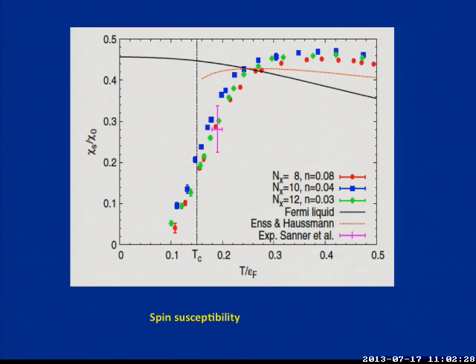If I'm at finite temperature, well above the critical temperature, the pairs are already broken, so there should be no effort doing this. And I can calculate from normal Fermi liquid properties. This is this result, the dash and the solid lines. Now, if I want to break a pair, this is kind of a local probe. It doesn't probe the coherence in the superfluid, which is long range, which at the critical temperature goes to infinity. So it probably senses something very local.